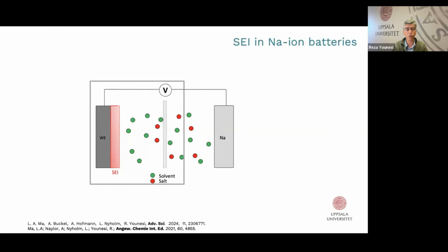Instead, what we have been trying to use is metallic foils as working electrode. This could be platinum foil, gold electrode, or glassy carbon. That was the first step, but later we also moved to practical electrodes like hard carbon, or model electrodes like carbon black electrodes with rather high surface area to increase the amount of SEI formed, and to try to understand what happens with SEI formation and dissolution.